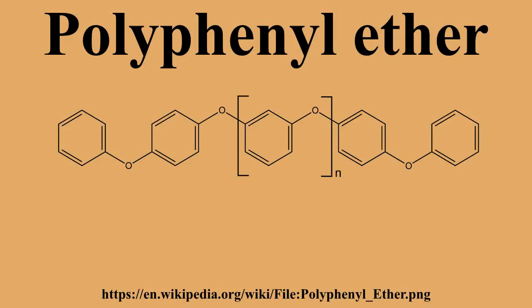A thin film of polyphenyl ether on a surface is not a thin contiguous film as one would envision, but rather comprises tiny droplets. This PPE property tends to keep the film stationary, or at least to cause it to remain in the area where the lubrication is needed, rather than migrating away by spreading and forming a new surface. As a result, contamination of other components and equipment, which do not require a lubricant, is avoided. The high surface tension of PPEs therefore makes them useful in lubricating electronic contacts.